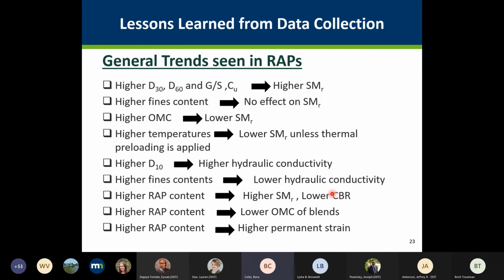So the general trends that we see and what lessons we learned from this data collection: in recycled asphalt pavements, the higher D30, D60, the gravel to sand ratio, and coefficient of uniformity resulted in higher resilient modulus values. I didn't show the graphs here, but higher fines content didn't seem to affect the resilient modulus of the RAP materials when they are used in pavement foundations.